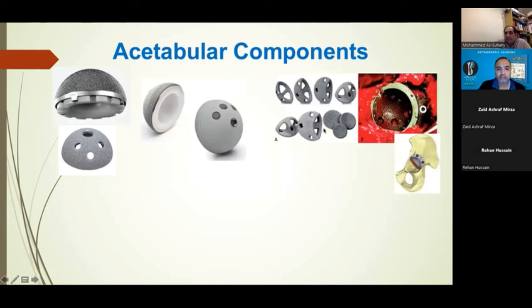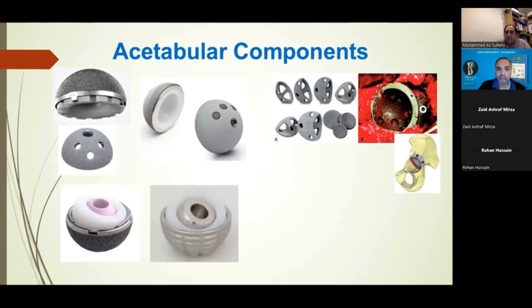This is a picture of what we call augments. So sometimes if you've got a bit of a bony defect, you can use these sockets, but you may be left with a bit of a defect. So you've got an option of using these little metal triangular sizes of different size. It depends on the defect size. You can then anchor that with a screw, and this is made of the same sort of porous material. And again, that will allow incorporation to host bone.